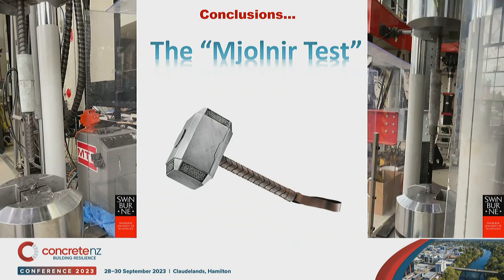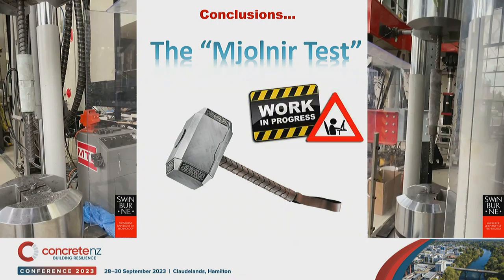So this is, of course, still a work in progress, that a lot of things can be refined. The initial test, also this one that you have seen, was quite different before we joined forces. So we changed a lot of the parameters, the temperature, the speed, and the requirements that we had for the strain rate. It's still a work in progress, but I think it's a good starting point for testing and proving if this is an issue, which is apparently something that is not recognized by other international standards, not even 15835 and 15698. But if it's a problem, we need to check if it's a problem or not. So performing the test, I think it's a good thing to do.